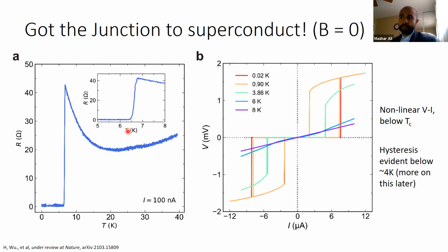The device critical temperature was almost 6.5 Kelvin. So actually relatively close to the Tc of the niobium diselenide itself. And we found that when you transition below the superconducting critical temperature, you start to see a nonlinear IV. Now it's hard to see in this blue line, which is at 6 Kelvin, but if you have eagle eyes, you can sort of see it. But obviously you can very clearly see it in the low temperature data.